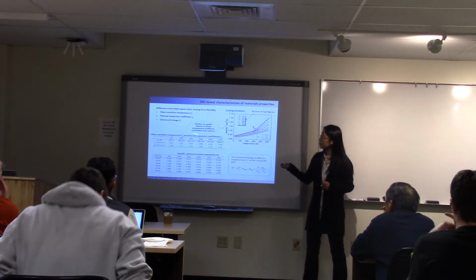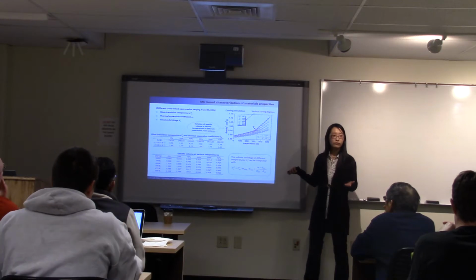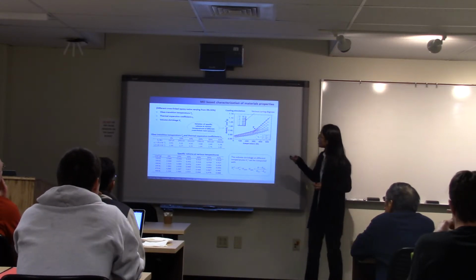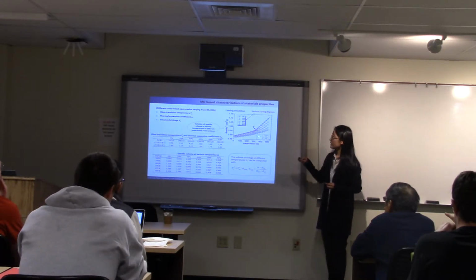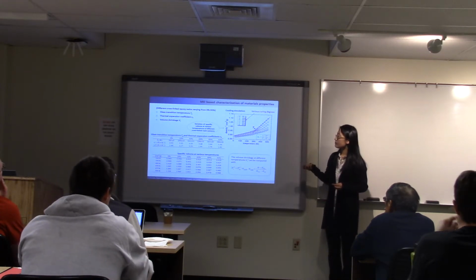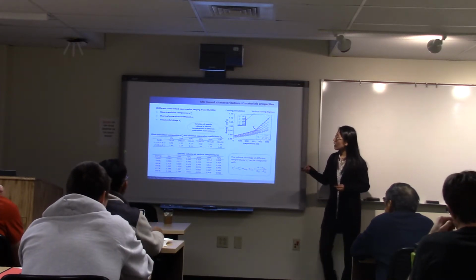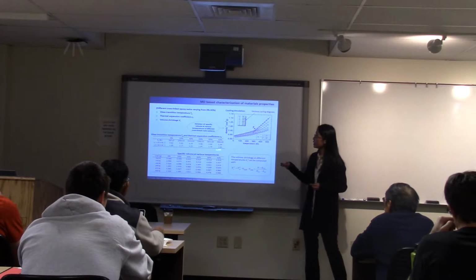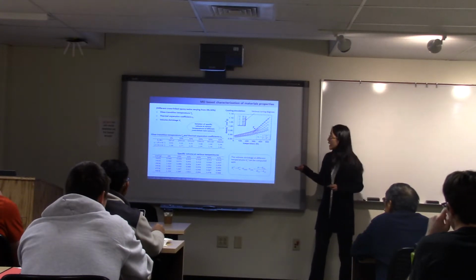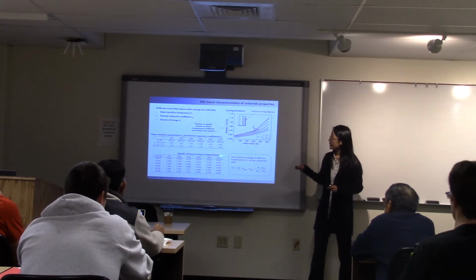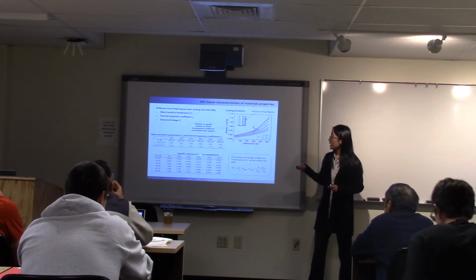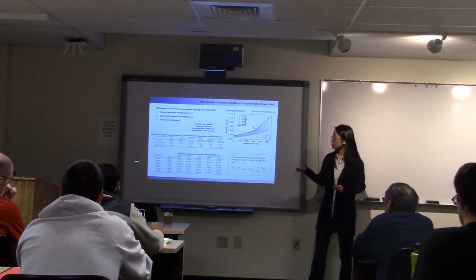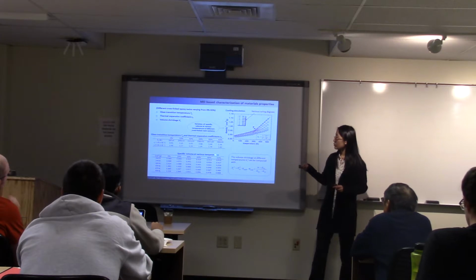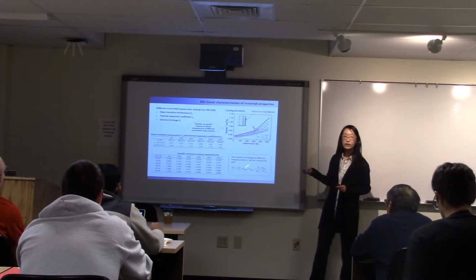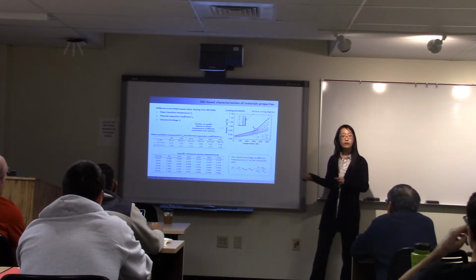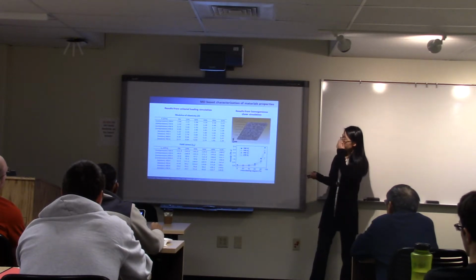Here we calculated it for the various cross-linking systems. Also, from the slope of the fitting line, we can get the thermal expansion coefficient. For the rubbery state and the glassy state, their values for the different cross-linking systems are given here. We can also get the specific volume at various temperatures and its change with the cross-linking degree, which could be fitted using this model and further used for the continuum simulation.